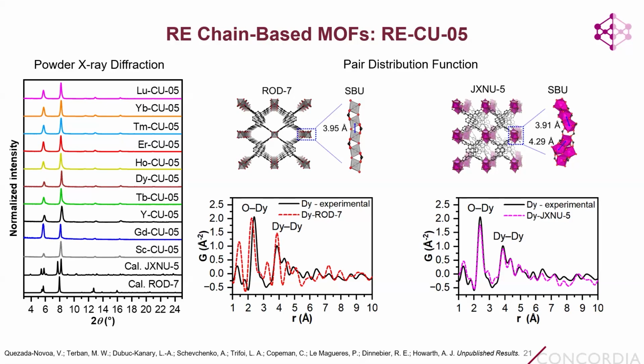And so what we can see from this pair distribution function data is that the local structure of CU-05 matches quite well with that obtained from the model for dysprosium JXNU5. And so if we combine that with the fact that the Pawley refinement also matches quite well for this MOF, we're now reasonably sure that the material that we have is isostructural to this MOF here.